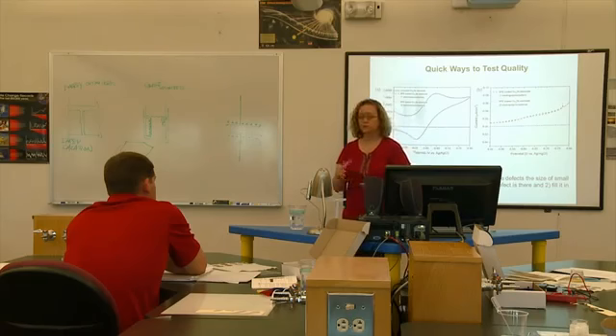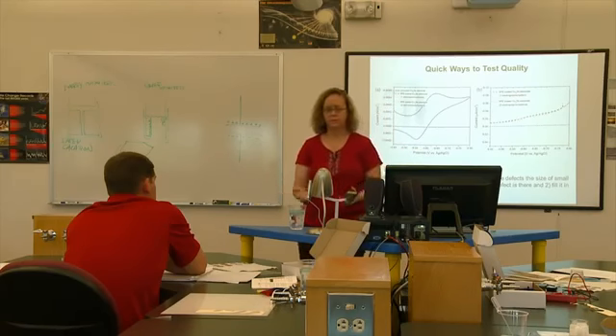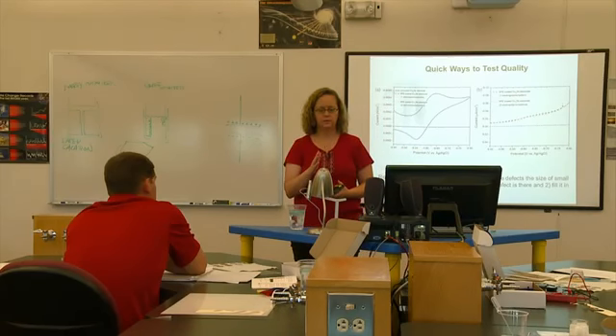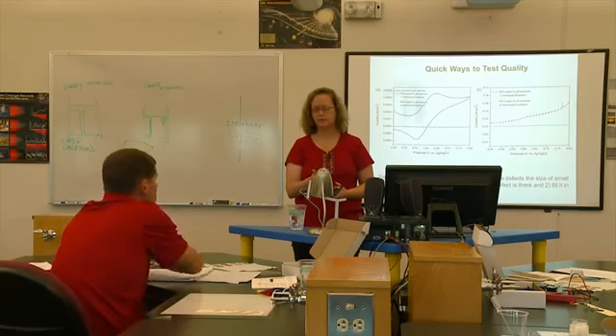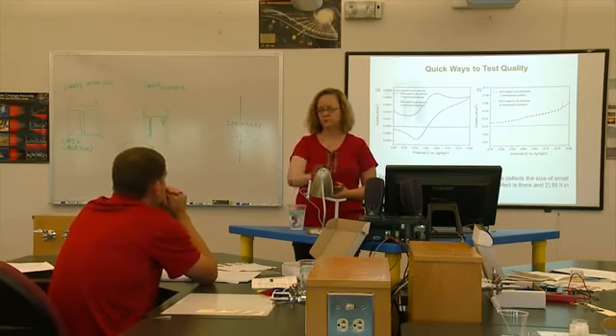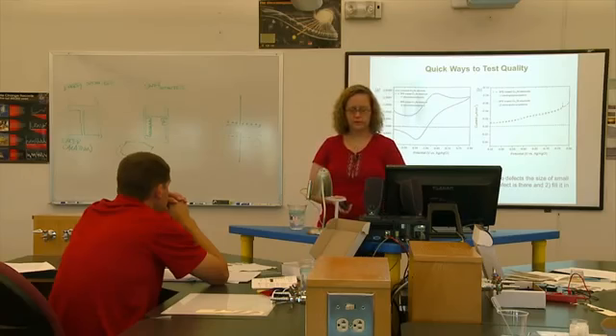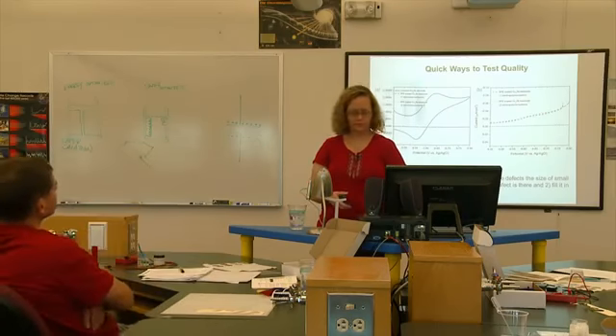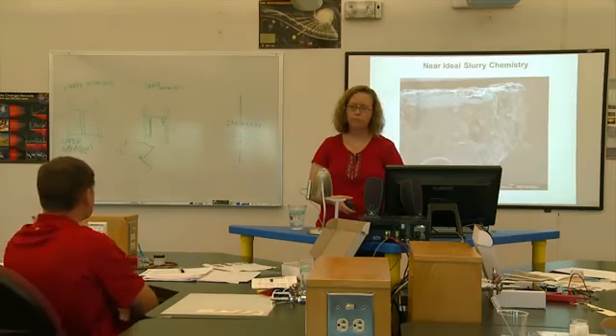So this is also all done in water. It's all done out open in air, and it takes about 30 seconds for the test, and then if you see a mistake, you have to rinse, that's a minute. You put it back in the polymer solution, and then the next pulse is about a 4-minute pulse, and then you just check it again. So this is how we know if a defect is there or not, and also how we fix it. How often do you get defects?